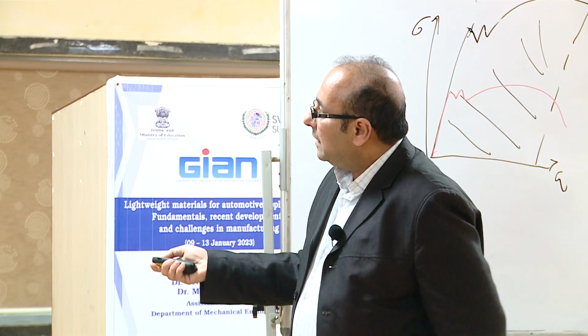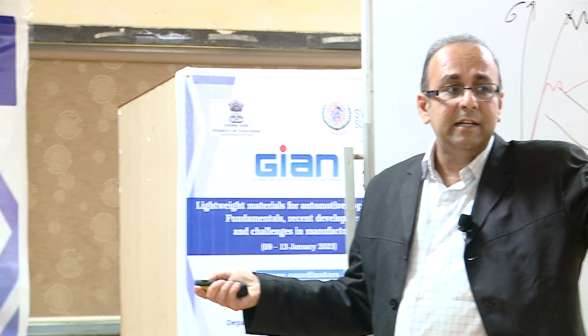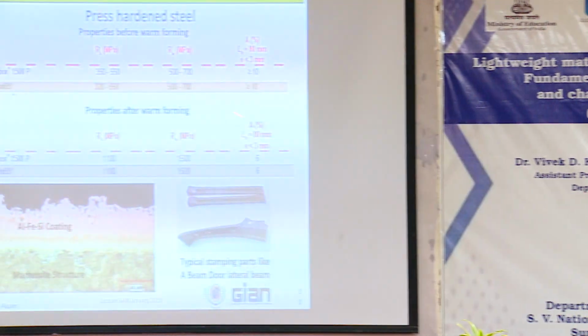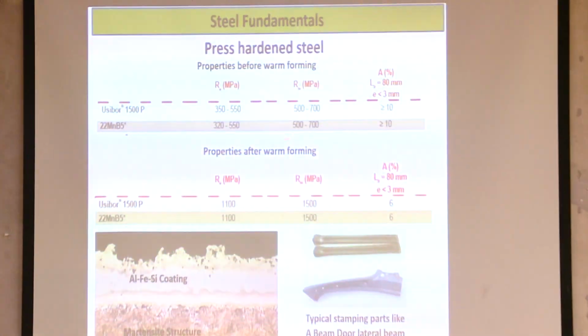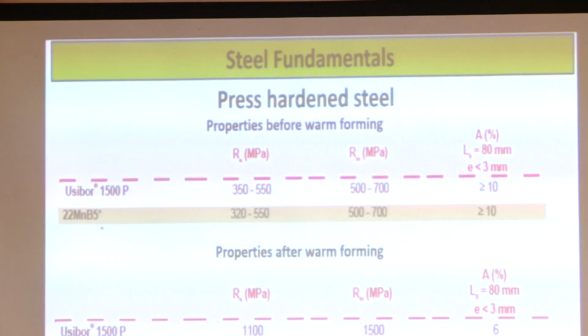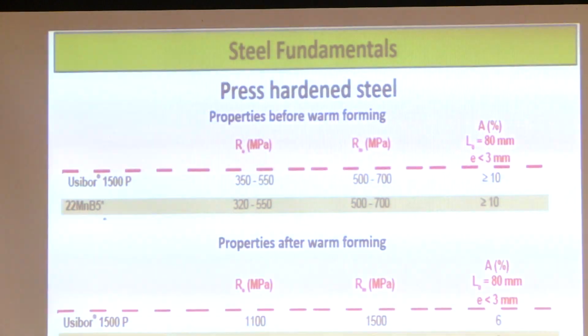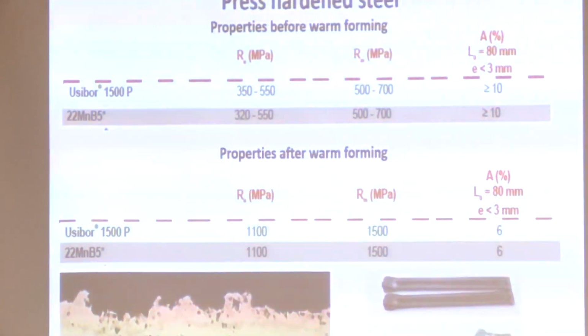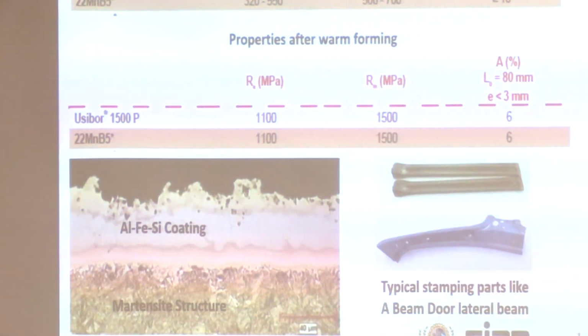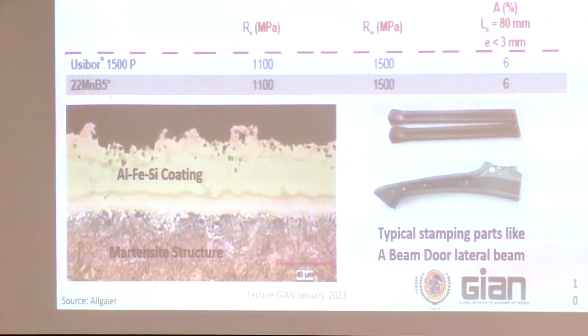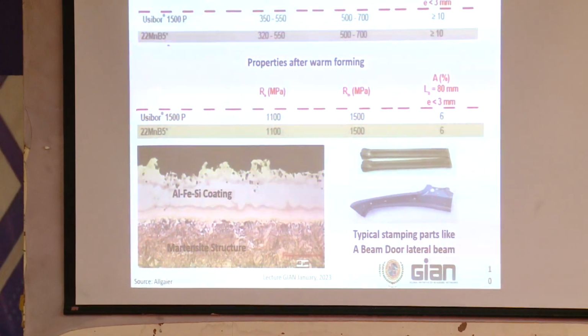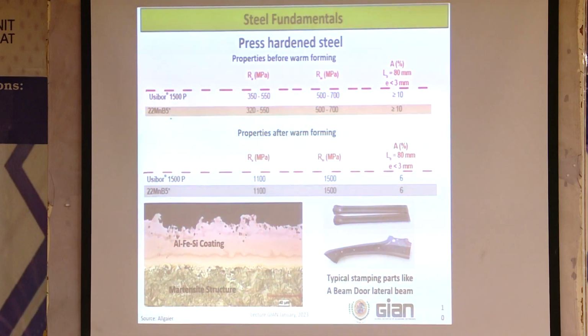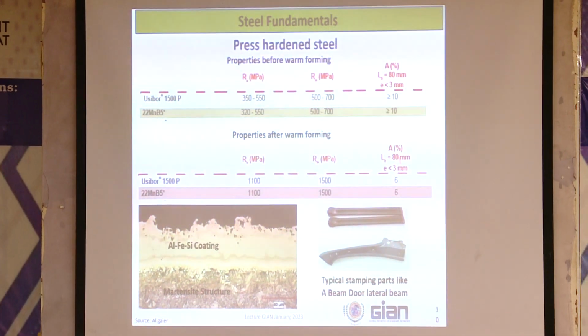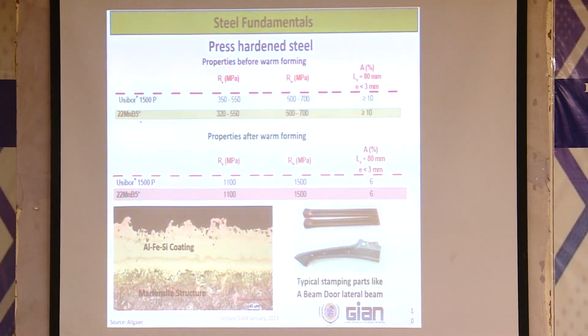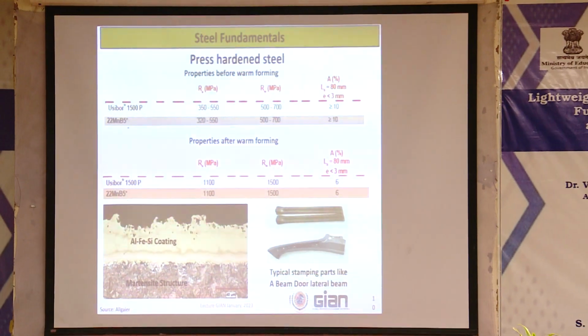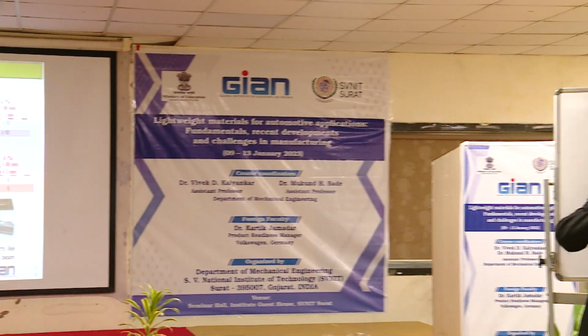Once you have this material, you can see that the initial phase, before it is formed, when it is in the delivered stage, you have quite good formability, around 10%. The strength is also not that high, 500, 700. So the original material is quite soft to handle. But then after deformation and after producing your final strength, you can see the difference in the yield strength. You go up to 1100, 3 times the strength. And that is what is actually important. Plus, very important, in spite of this strength, you still have around 6% to 10% elongation left. It means it cannot produce fast cracks.